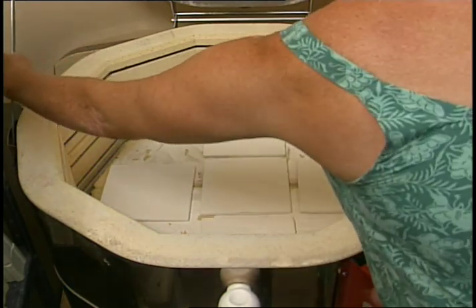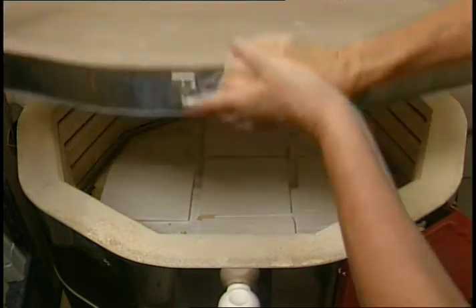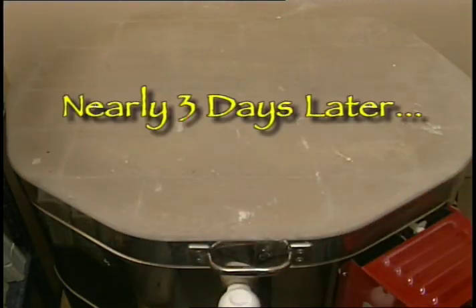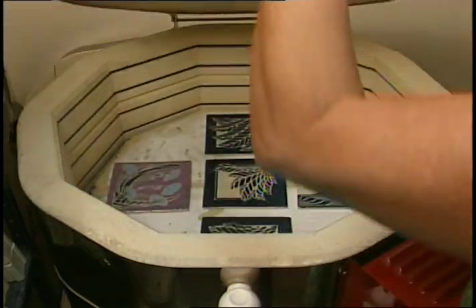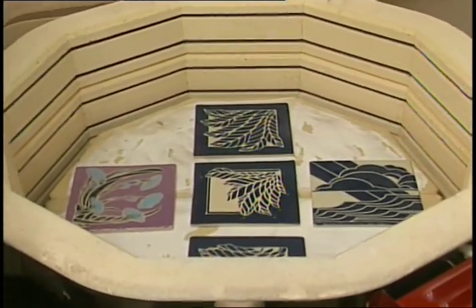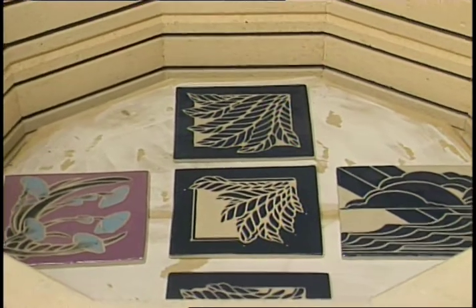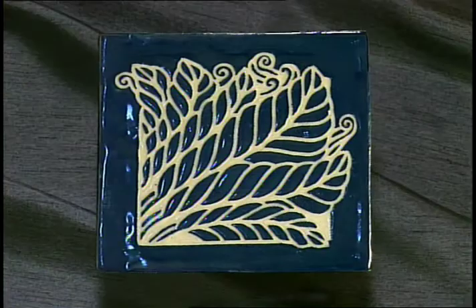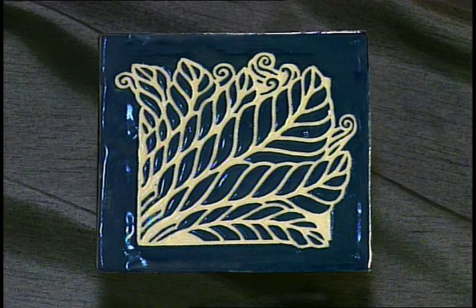After they're glazed, and I place them in the kiln, turn the kiln on, I have no control of the process. In the glaze fire, the pieces are fired to almost 2200 degrees, and it takes almost 24 hours for the kiln to heat up, and then a very, very slow cool down. So the glaze fire takes almost 3 days.